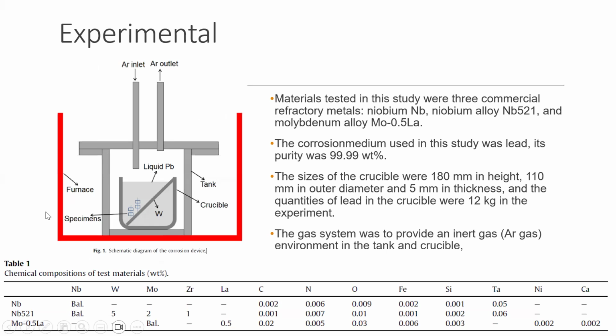This is a schematic diagram of the corrosion device. The materials tested in the study were three commercial refractory metals: niobium, niobium alloy, and molybdenum alloy. The corrosion medium used in this study was lead. Its purity was 99.99%, and the size of the crucible was 180 millimeter in height and 110 millimeter in outer diameter and 5 millimeter thickness.